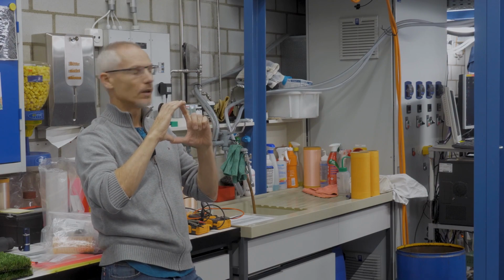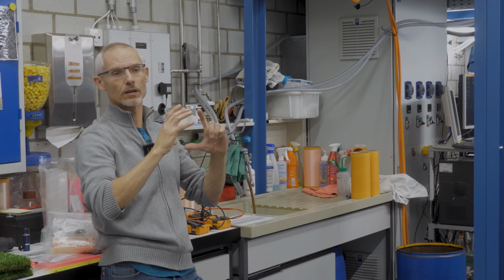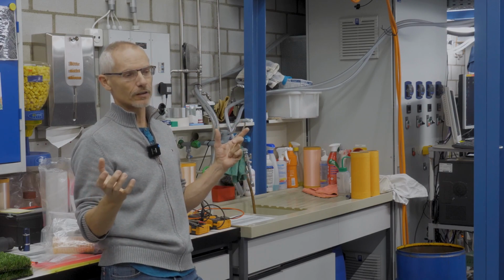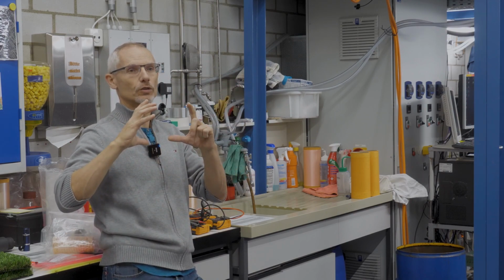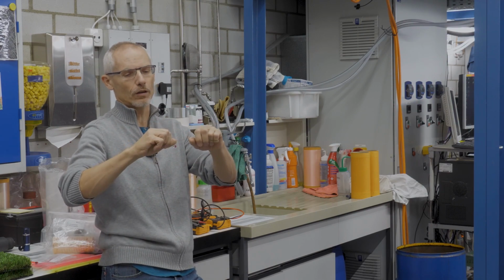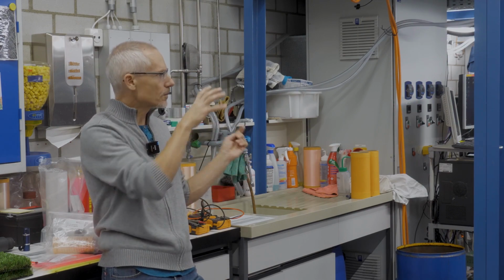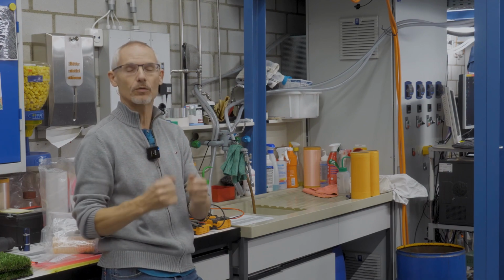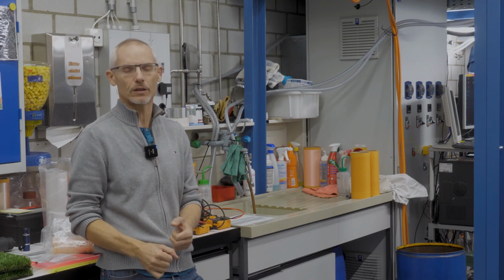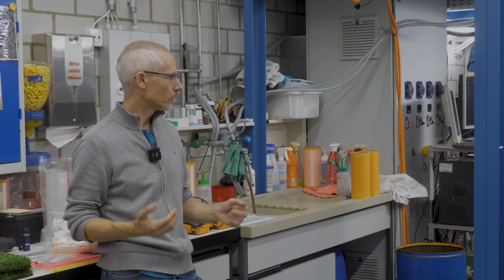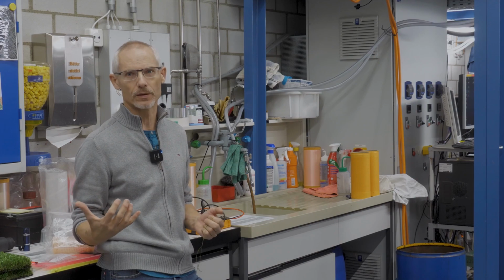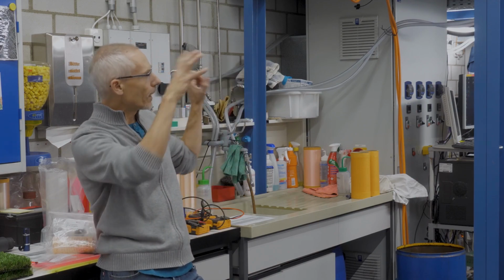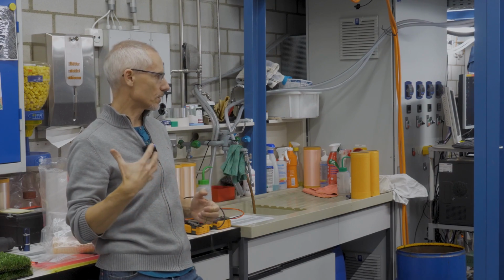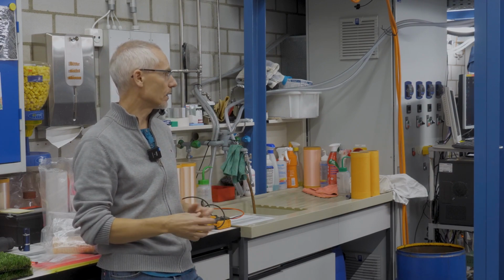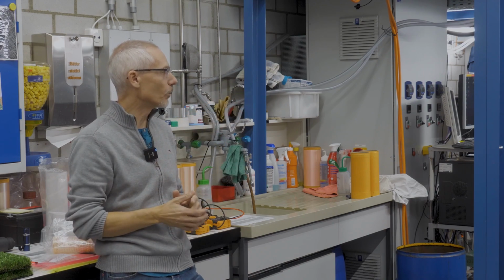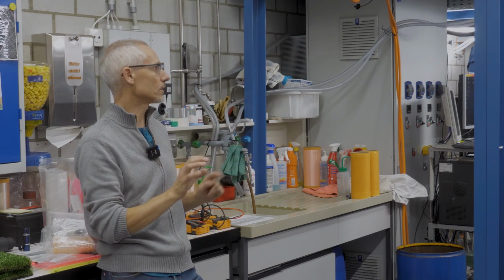and we do that by winding it around these moving cylinders. And when, for example, the first take-up cylinder has a speed of, let's say, 500 meters a minute, and the last cylinder of 2,000 meters a minute, we have a drawing factor of 4. So just by adjusting the speeds, we can decide how much we want to draw the fiber. And the more we draw it, the stiffer it gets, and with that we can decide about the tensile properties of a fiber. So apart from the extrusion, we also have the drawing, which is the drawdown unit, which is also very, very important. And as you can see, we have the possibility to easily modify the setups of the cylinders, the speeds, temperatures, everything.